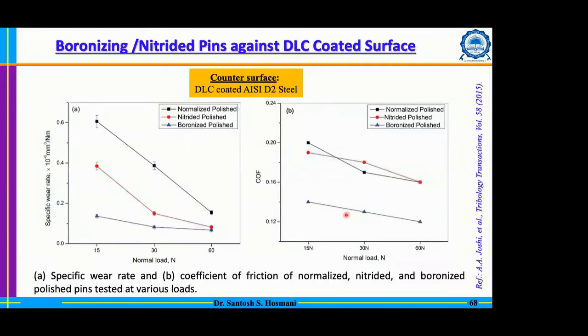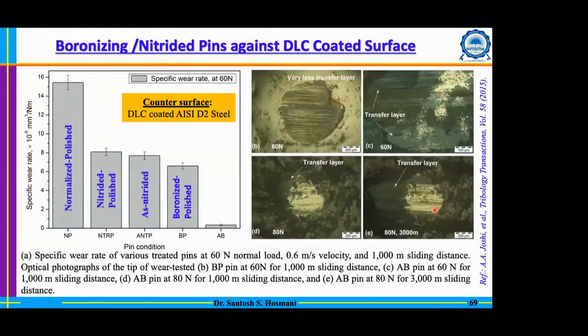So this same thing we actually mentioned, and here you can see that your performance keeps on improving as you keep on raising the load. That is the beauty of DLC coating, because as you keep on raising the load, you have more and more transfer film, a carbonaceous film, which forms at the interface, and that is helping us to improve the property. Okay, and here, in this comparison with respect to your nitrided sample as well as a normalized sample, you can see that the AB pin, that is the boronized surface against the DLC coated D2 steel, extremely good behavior has been observed, especially for this particular situation.